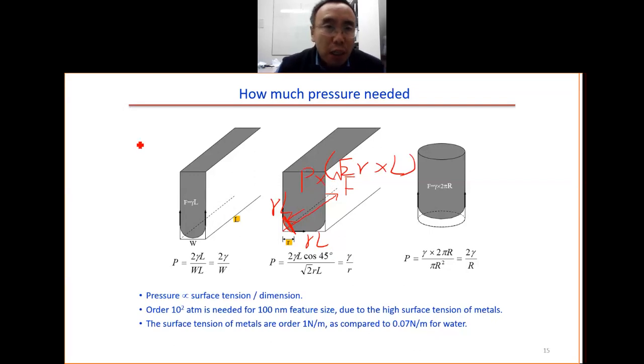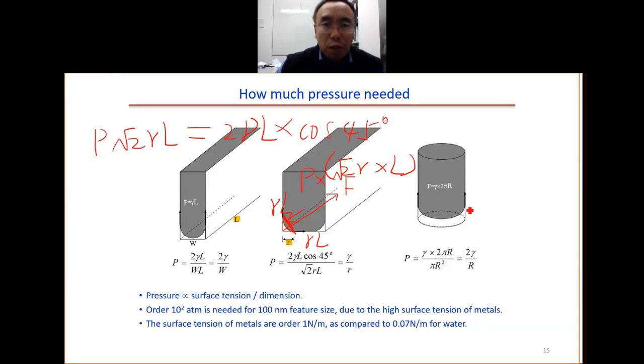That means this force, P times square root of 2R L, equals 2 gamma L, 1 gamma L here and another one here, times cosine 45 degrees. Because this force points up, and this force points along this direction, we have this 45 degree angle here. So you can cancel out the L. In the end, you get this formula, gamma over R. P times square root of 2R L equals 2 gamma L cosine 45 degrees. You get this formula.